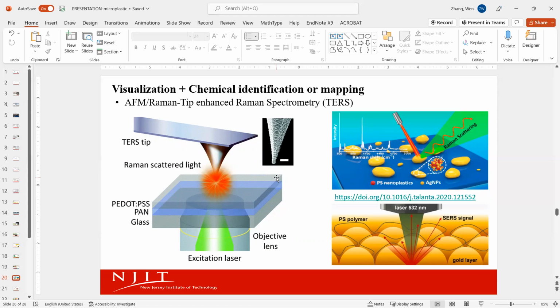We just previously talked about surface-enhanced, where on the substrate surface you put some gold or silver, right? The other way you can do it is you have a tip, right? The tip may not be an AFM tip, but generally it is called a TERS tip. It's pretty large. So on the scanning tip, you can coat it with platinum, gold, or silver, some noble metals. Once you use the tip to probe the sample, and in the meantime you shoot a Raman laser beam here, then you can have an enhanced Raman signal. This is called the tip-enhanced Raman phenomenon.